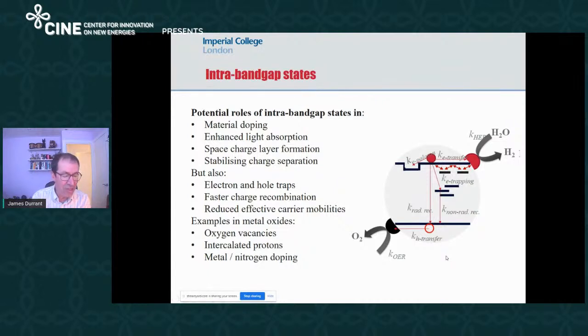Now, in terms of thinking about the materials, one of the biggest challenges of oxides is they're full of defects. You can see some examples of this here: oxides have deep traps, they have shallow traps, and many of the materials which we're interested in have defect states. We're interested in materials which are highly scalable, highly processable, which don't have large embodied energies in their fabrication. And these tend to be more defective materials.